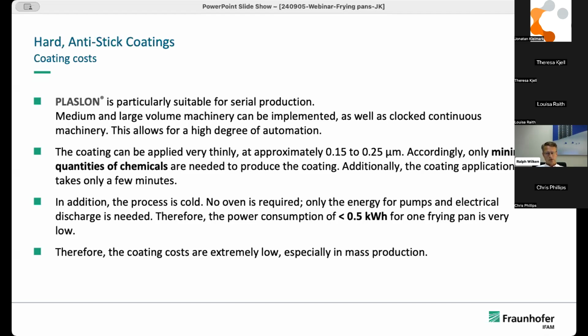The coating itself is also quite fast, takes only few minutes. In addition, the process is cold. We do not need any curing step, no oven or so. We only need some energy for pumps and the electrical discharge. For example, if you calculate the power consumption of one frying pan, it's less than half a kilowatt hour. Therefore, the coating costs, the running costs are extremely low, especially in mass production. Next slide, please.